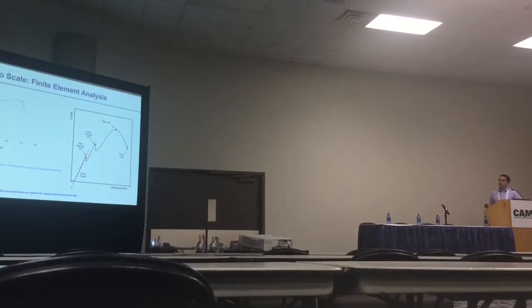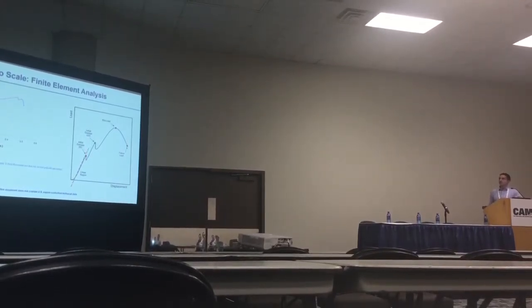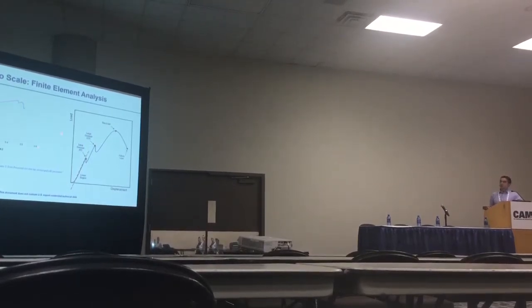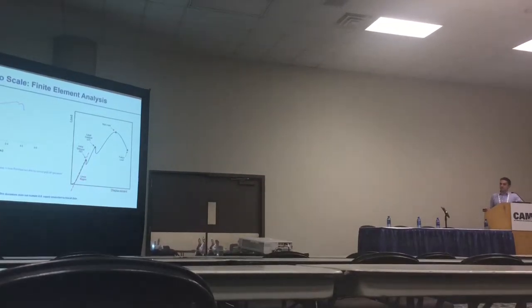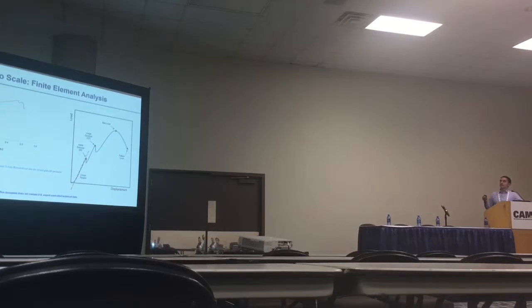When I get that, it feeds into the finite element approach. To get an allowable, you need to define the failure. In my case, I am stating that the failure is the first drop in a load displacement curve. So if I was able somehow to run a simulation that generates displacement versus load, like this, and run it to some failure scheme, that would be my allowable, okay?